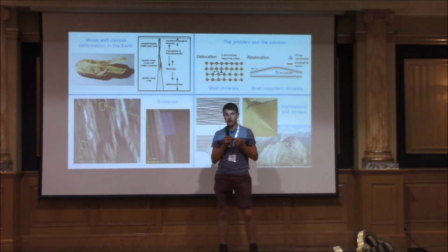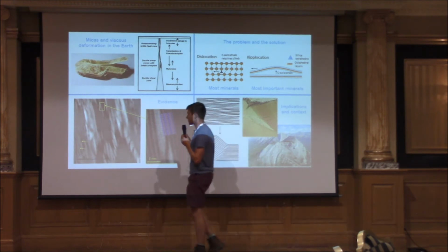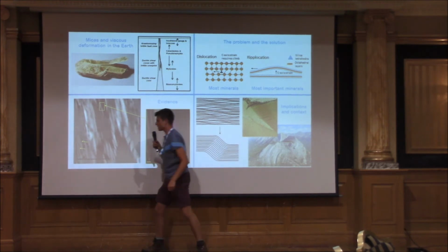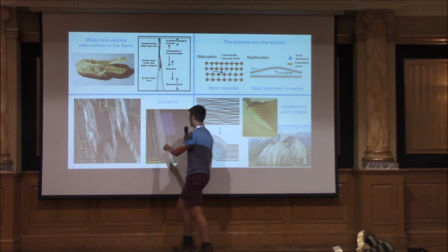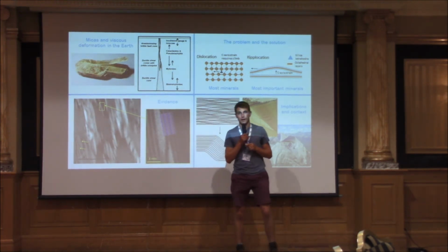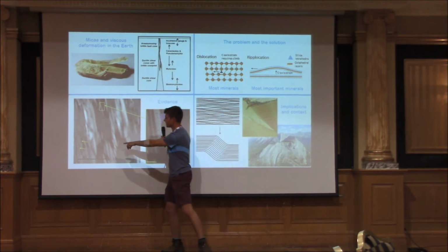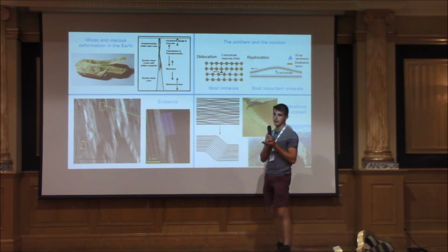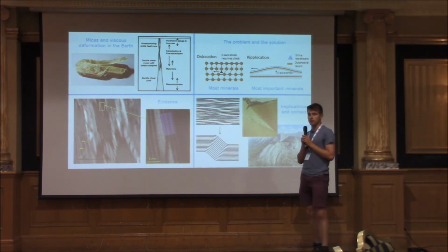In my research recently, we believe we've found the first evidence of these mechanisms, these reptation in natural minerals. And so this image here, that's a 50 nanometer scale bar, so it's a bit dark, but that scale bar there is 1,000th of the width of a human hair. And what you're looking at here, again, it's quite dark, but these are individual layers of atoms and part of the lattice planes within the mica structure. And you see this curvature and deformation and structure that we see here can only really be explained by reptation, not by dislocations.